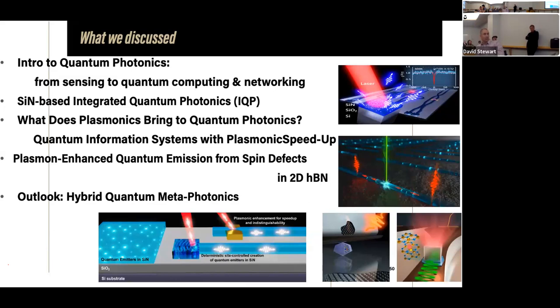However, with plasmonics, you could go truly to electronic-like confinements. These gap plasmons could confine electromagnetic excitation down to 2-3 nanometers. This is the size of a transistor, and you get this Purcell enhancement. And the frequency would be optical. So the world is changing. I'm not saying that photonics solves all the problems, but at least it's complementary to the existing electronics in terms of speed. And in terms of coupling, the way to address it, use this confinement, and particularly plasmonic confinements. So you have, as a result, oscillations of optical frequencies, which are spatially confined to a size, let's say, like 2 nanometers. Something you cannot do with electronics.